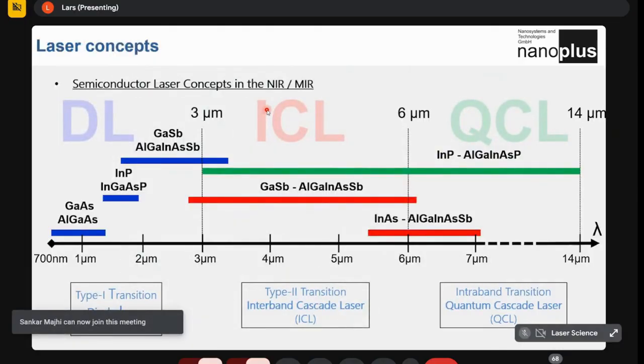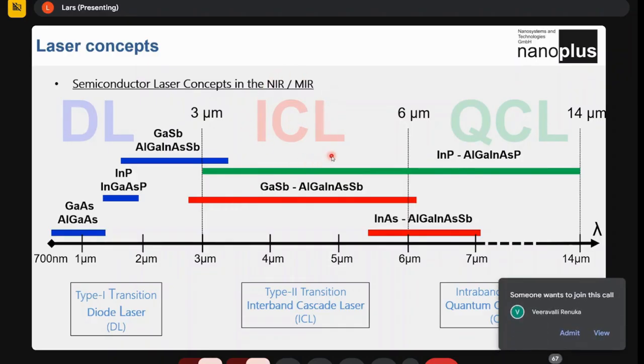There are different laser concepts available. If you go down to the 700 nanometer range, we're using gallium arsenide or aluminum gallium arsenide chips. Going further up to higher wavelengths, you can use indium phosphide or gallium antimonide up to 3 micrometers. Then between 3 and 6 micrometers, you're using interband cascade lasers, ICLs. These are type 2 transitions.